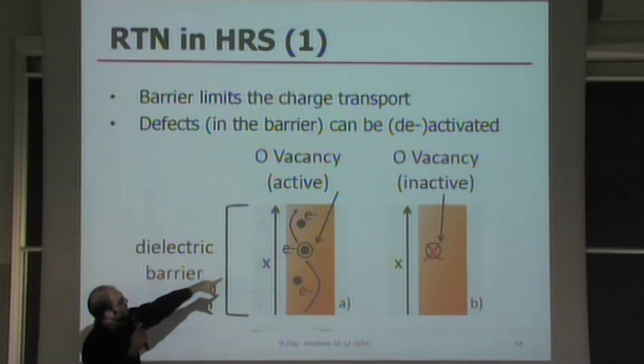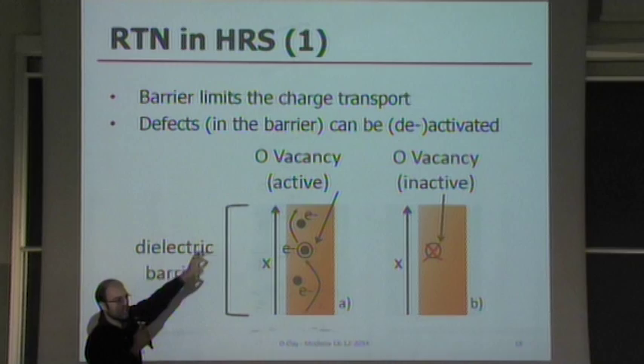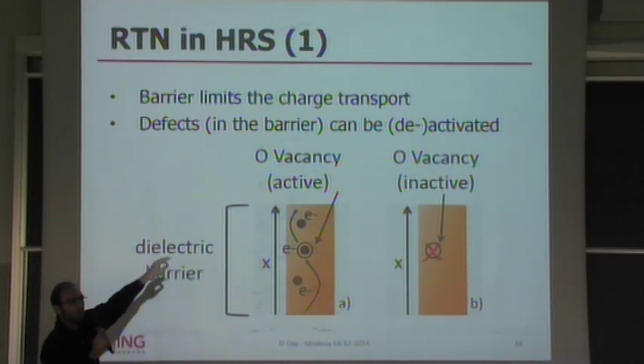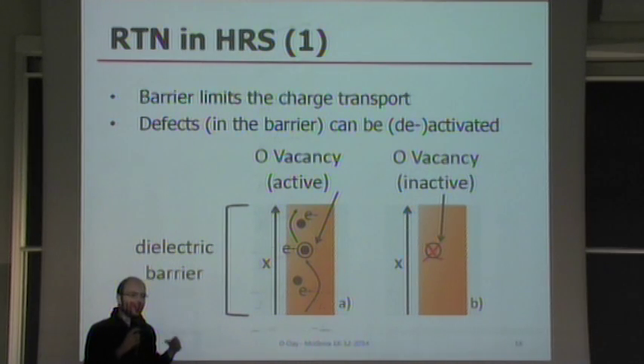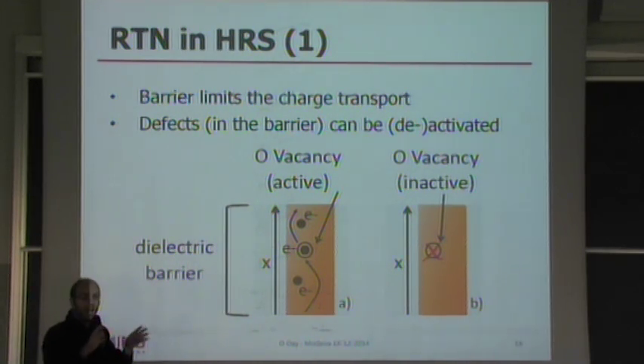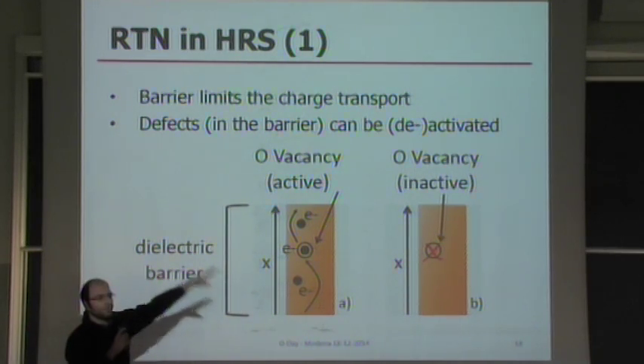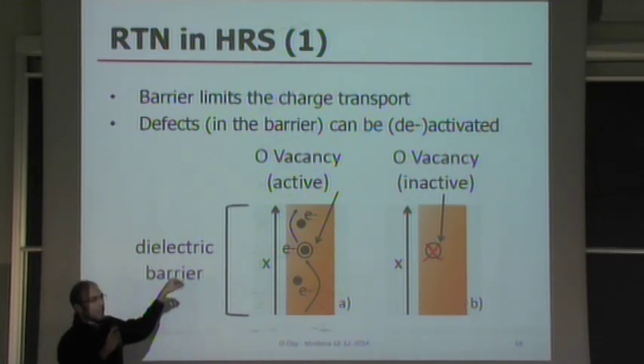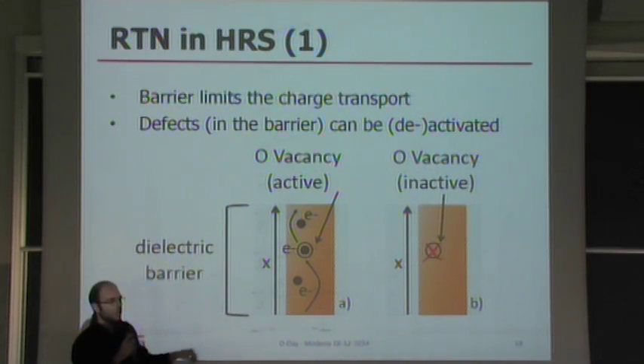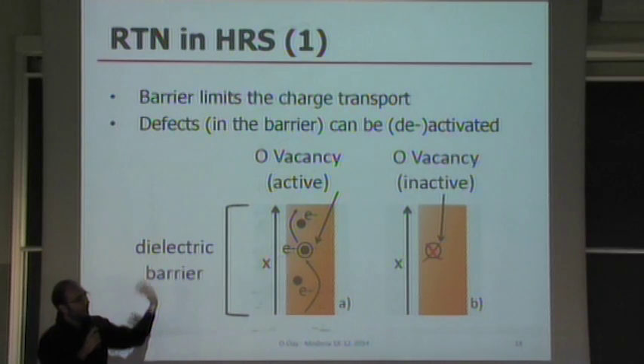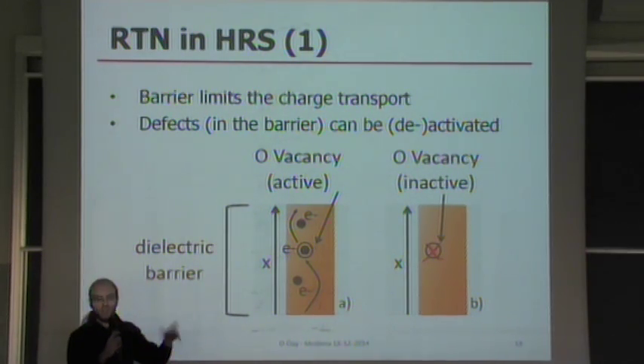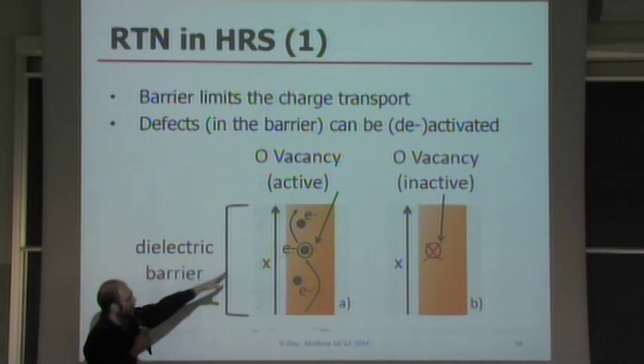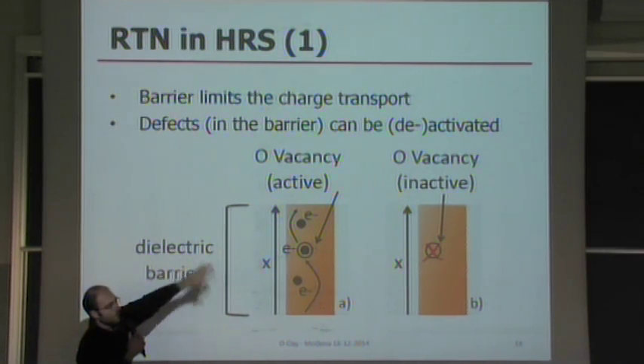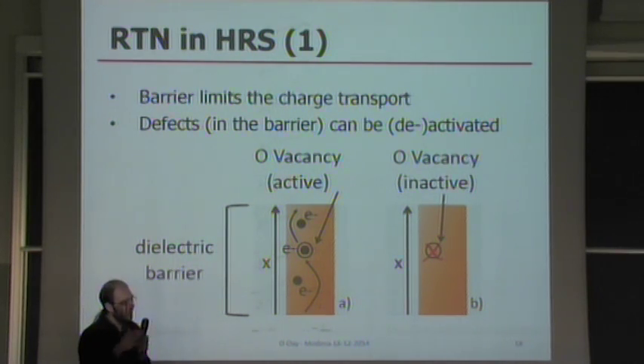And in the barrier, we have oxygen vacancy defects, which are assisting the current with very, very fast capture and emission processes. Now, it has been assumed in the literature to explain the RTN that for some unidentified reason, this defect may be randomly deactivated. So they are driving some current, they get deactivated, they don't carry any current anymore. But then they can get, for some other reason, reactivated and then can join current conduction again. There's plenty of oxygen vacancies driving current into the barrier, but they can get somehow activated and deactivated. The question is how? And this is still unanswered. We will end up having a proposal for that.